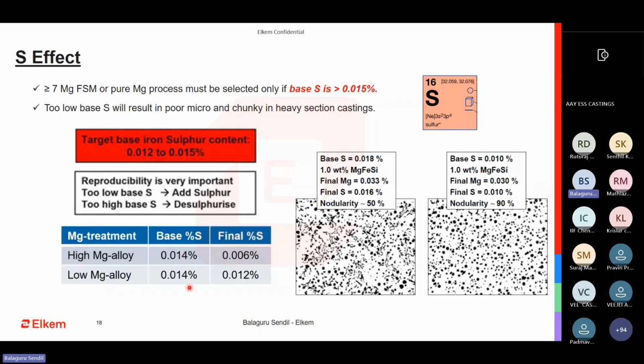A low Mg alloy will not drastically drop your sulfur. Your sulfur level is maintained in the foundry. When you have a consistent sulfur and your sulfur drop is also not significant, you have a very good microstructure here. You see a base sulfur of 0.01 and then you have a final. This is the output. There is not that much of a drop between base and final. The sulfur value is the same. That means that in the 0.030, most of it has been converted into MgS, which is very small, and it is measured as a part of the final sulfur.